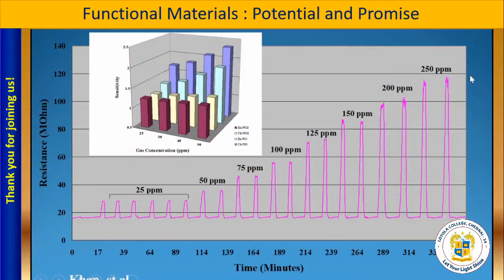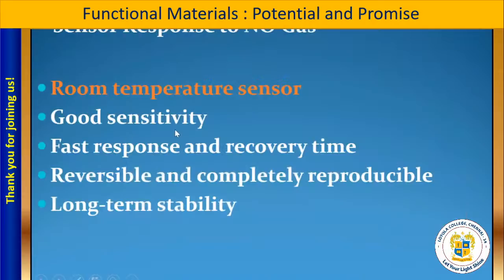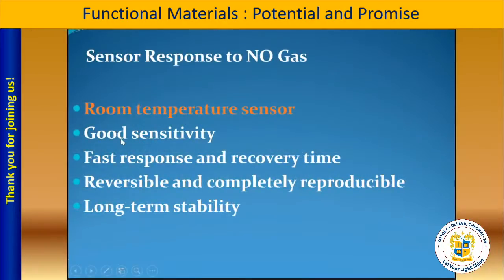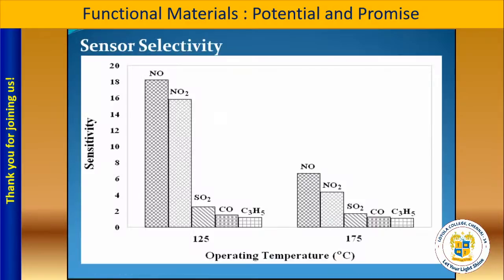And the response of the sensors covers the entire range. So this is a new class of sensor materials, and they operate at room temperature. Yes, at room temperature. Most of the other sensors operate at 200 to 400 degrees, needing continuous energy. Here, there is zero energy. So this is again a tremendous functionality of the material. So our sensor materials are room temperature NOx sensors with good sensitivity, rapid response and recovery time, long-term stability, and complete reversibility and reproducibility. This is something unheard of.